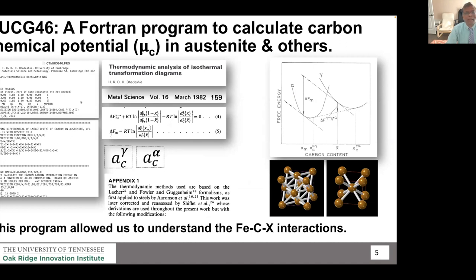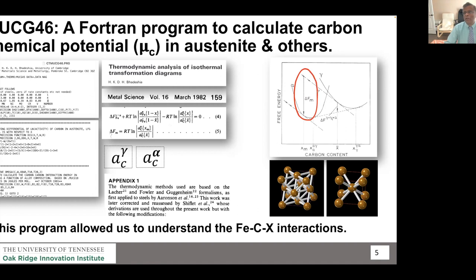What is MUCG 46? You can see this is a Fortran program — the typical inputs are carbon, silicon, manganese, nickel, molybdenum, chromium, and vanadium. It calculates the activity of carbon in austenite: MU is for chemical potential, C is for carbon, G is for austenite — that is where it all started. This allows us to calculate the driving force for ferrite to come out of austenite, triggering TTT diagram calculations. The key concept is para-equilibrium activity of carbon, which lets us figure out the role of substitutional elements on carbon activity, enabling steel and consumable design.